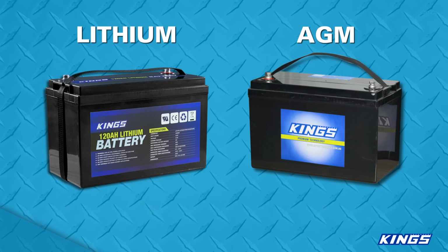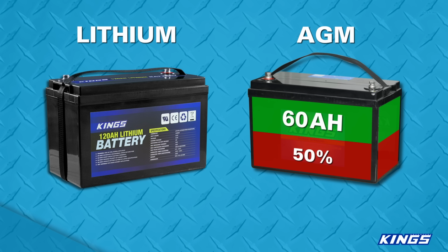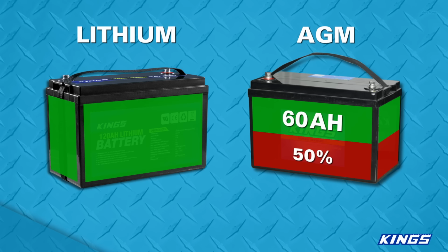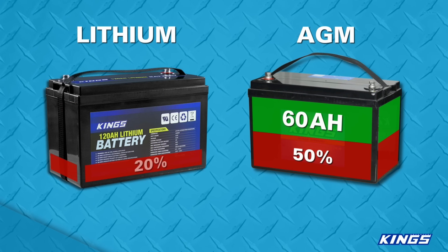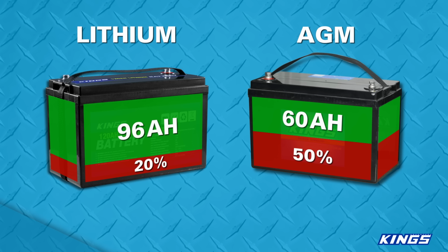If you're talking about recommended use, generally an AGM is recommended to only use 50% of its overall capacity, meaning you'd get about 60 amp hours out of this battery. A lithium ferrous phosphate's recommended capacity is about 80%, so you get 96 amp hours out of this lithium iron phosphate battery. That's 60% more power.